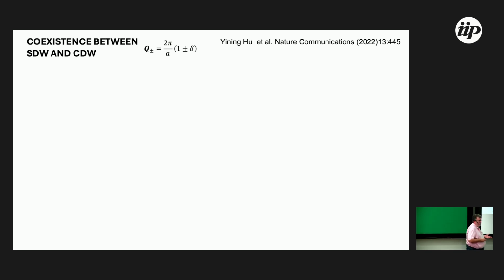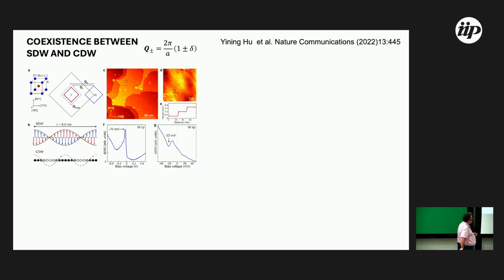Associated with the spin density wave there exists a charge density wave, because of the modulation of the spins associated with the modulation of the electrons. In chromium, this charge density wave is measured directly by STM measurements. The length of the spin density wave is around 6.0 nanometers, 60 angstroms, 20 times the lattice parameter of the chromium.